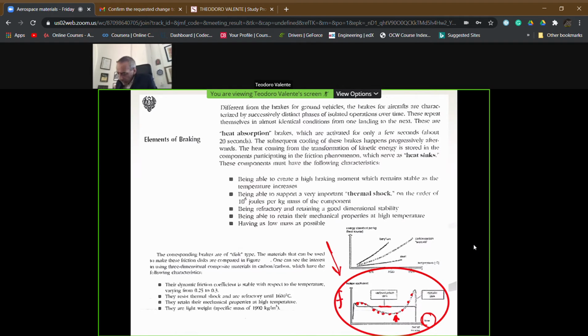If we use carbon-carbon, we have a very different behavior, because you see here a very large area in which the friction coefficient is stable. So you can use your brake for a longer time without any degradation of the braking performance. What changes is the first part of this curve, which you see here. We need to bring our system to a suitable temperature in order to have this behavior of a constant value of the friction coefficient.